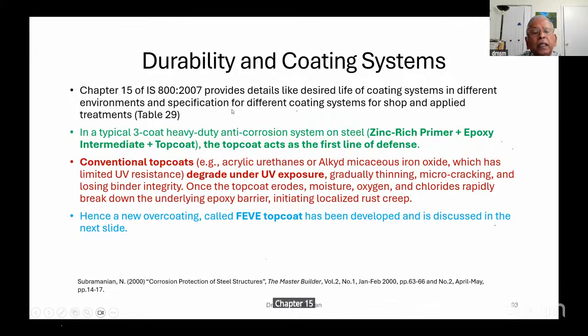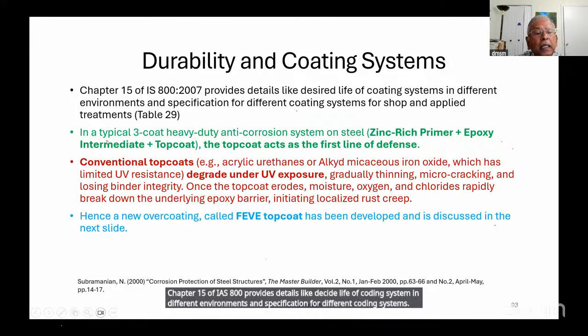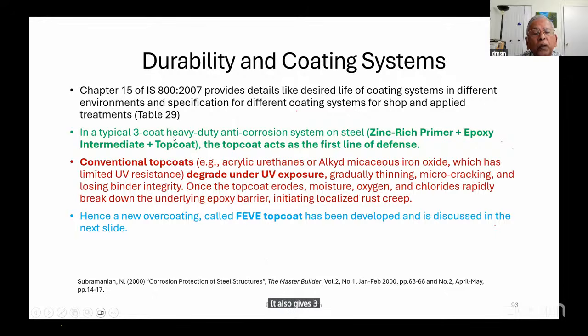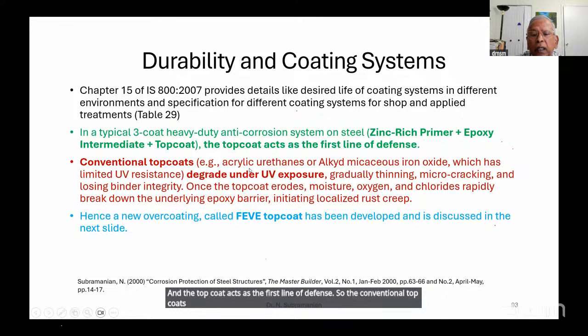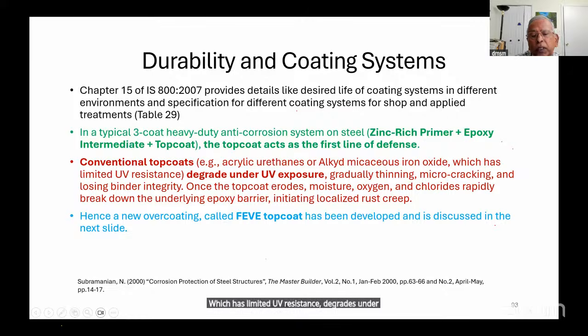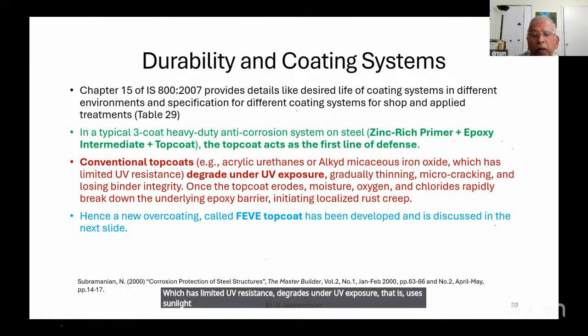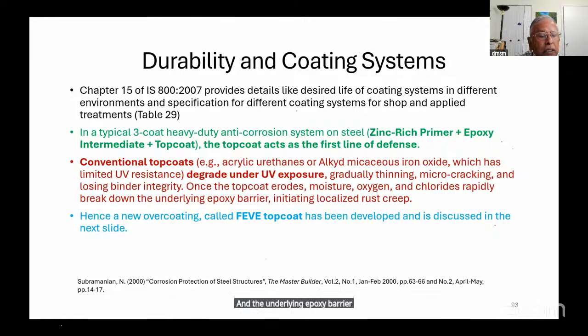Chapter 15 of IS 800 provides details like the desired life of coating systems in different environments and specifications for different coating systems. It also gives that a 3-coat heavy duty anti-corrosion system is required, and the top coat acts as the first line of defense. So the conventional top coats like acrylic urethane, which have limited UV resistance, degrade under UV exposure, that is due to sunlight, gradually thinning, micro-cracking, and losing binder integrity. Once the top coat erodes, moisture, oxygen, and chlorides rapidly break down the underlying epoxy barrier, initiating localized corrosion.